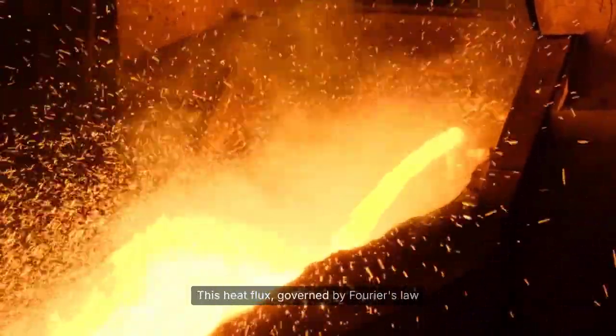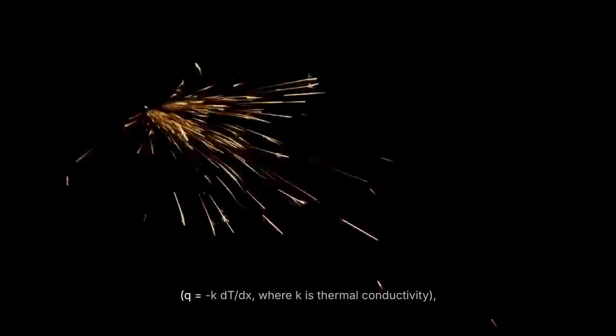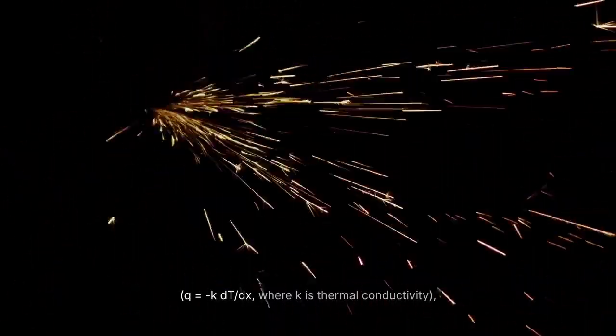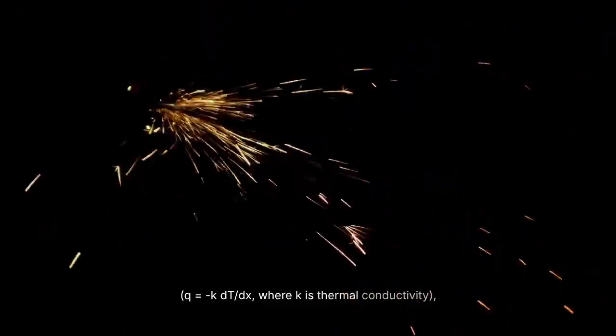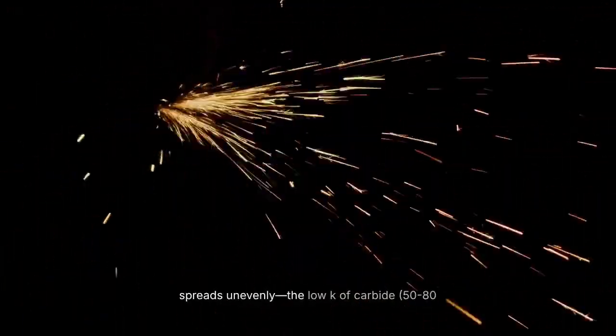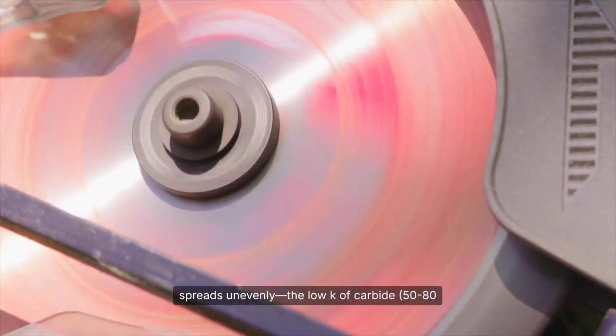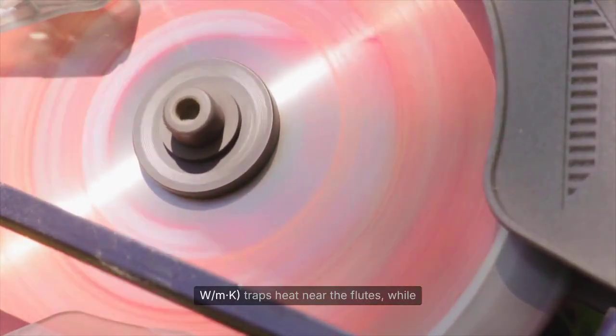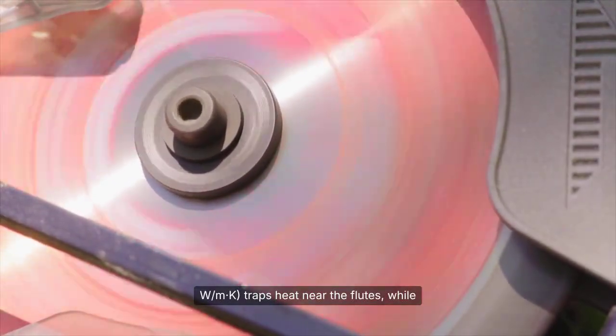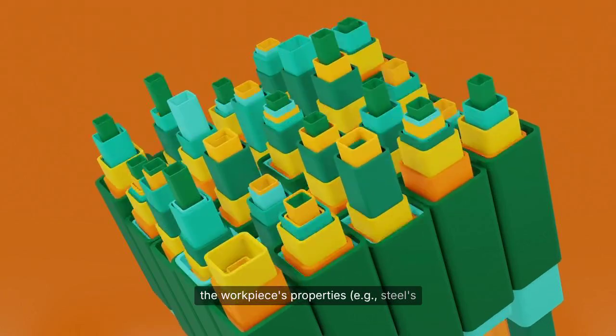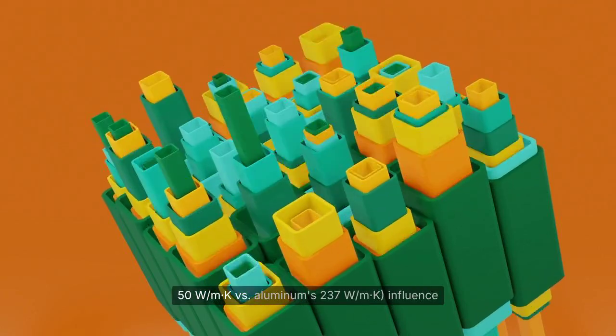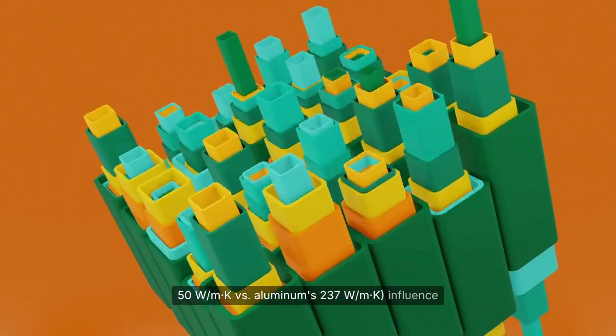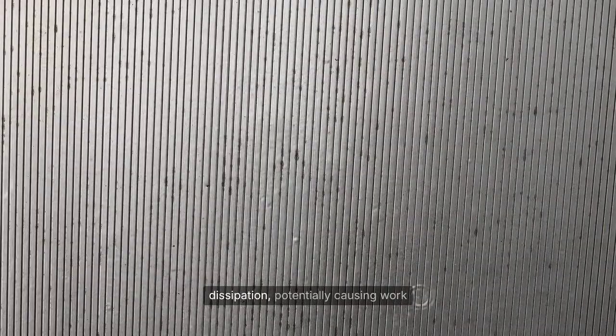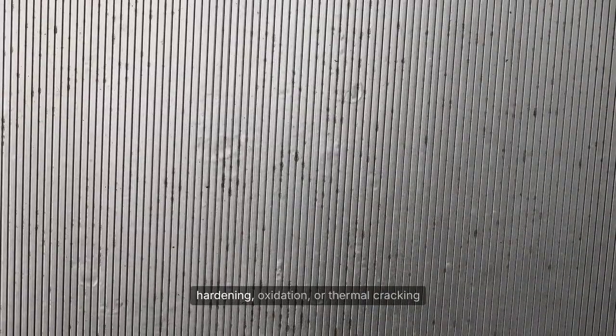This heat flux, governed by Fourier's law, Q equals minus K dT over dx, where K is thermal conductivity, spreads unevenly. The low K of carbide, 50 to 80 watts per meter Kelvin, traps heat near the flutes, while the workpiece's properties, e.g., steel's 50 watts per meter Kelvin versus aluminum's 237 watts per meter Kelvin, influence dissipation, potentially causing work hardening, oxidation, or thermal cracking in sensitive materials like titanium alloys.